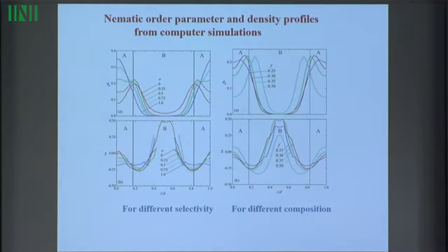And then, again, some curves for the nematic order parameter have been extracted from simulation. They cannot be compared quantitatively with the theory, but qualitatively they look similar. You see that indeed it is slightly negative on one side of the boundary, and then it is much bigger and positive on the other side of the boundary.